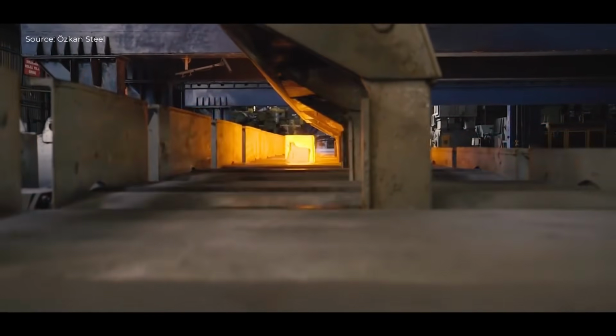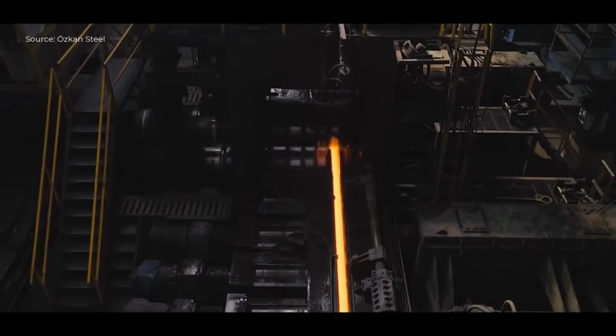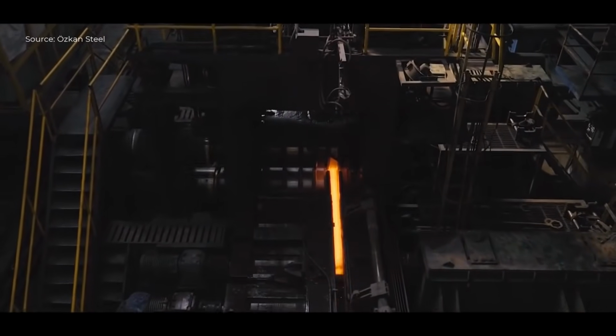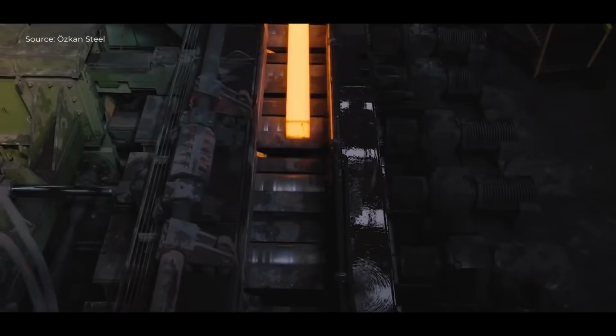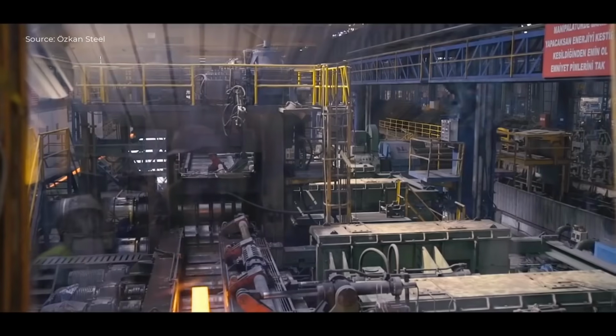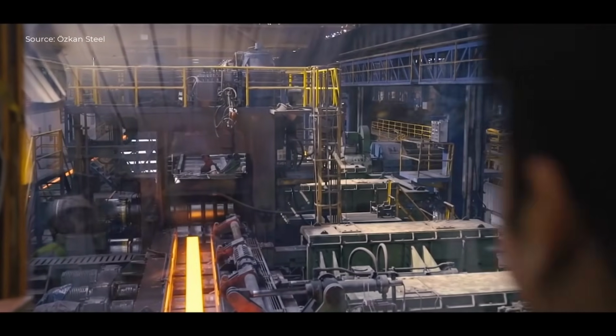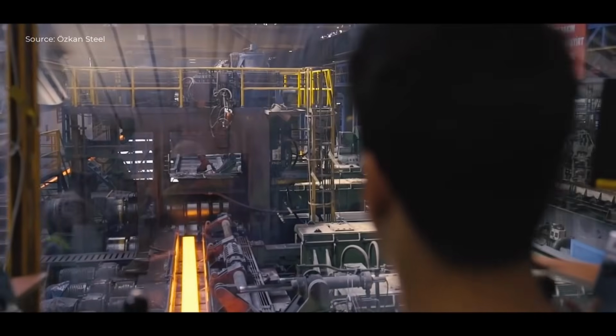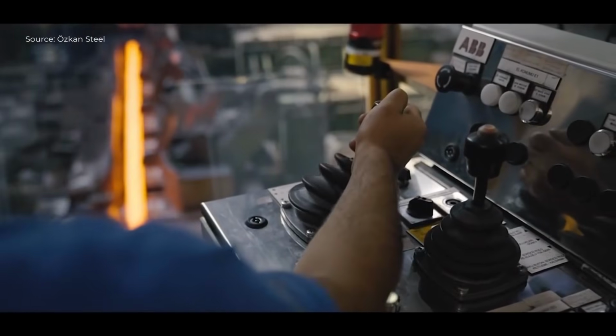The partially solidified strand exits the mold and continues through a series of secondary cooling zones. Water sprays control the cooling rate, ensuring internal structure consistency and preventing cracks. Gradually, the strand solidifies completely into square billets.